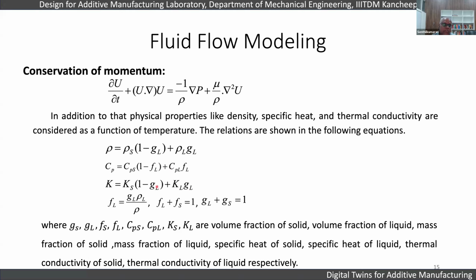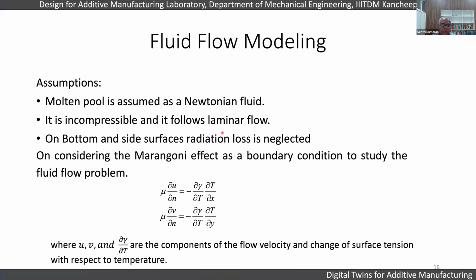So then we can use these input properties in the simulation to simulate the fluid flow. And many times, as I said, in thermal and thermomechanical simulations we make a lot of assumptions. Here also we assume it is a Newtonian fluid, incompressible, and follows laminar flow. And then we also give an additional boundary condition for the Marangoni effect, which is going to drive the fluid flow in the melt zone. So these are the conditions.